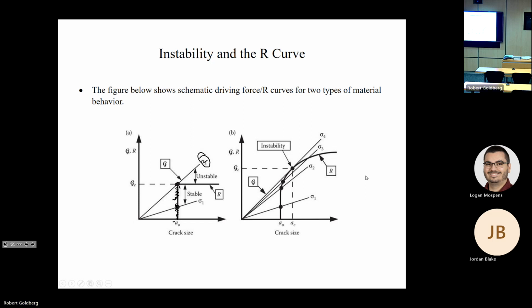Now, the second case represents a material with a rising R curve. So what happens here is your resistance stays constant for a while, and when you hit the sigma 2, the resistance grows a little bit, but it doesn't go crazy. So the crack can't grow any farther unless the stress increases. And when the stress is fixed at sigma 2, the resistance, this black curve here, grows faster than the driving force. So the driving force is growing, but the resistance is growing at a faster rate. So obviously, if the resistance is growing at a rate faster than the driving force, you're not going to have unstable crack growth. Things will still be under control.